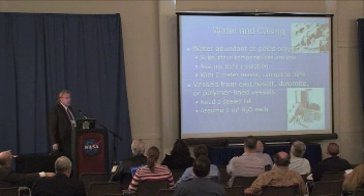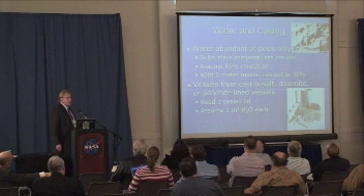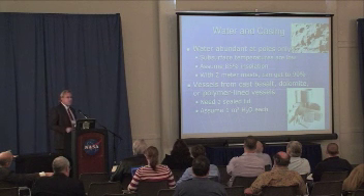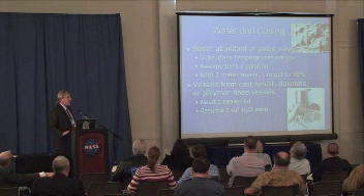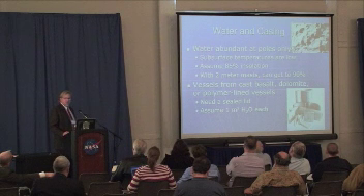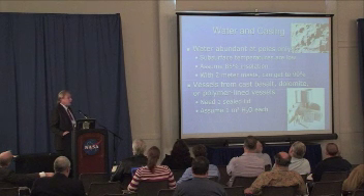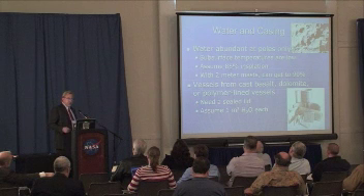The vessels can be made from cast basalt. Cast basalt is used traditionally on the Earth. What we're showing here are some cast basalt crucibles and other different kinds of structures that have been made from melting this material and squishing it into a form. You can make this into a vessel. The neat thing about this is that cast basalt can withstand up to 50% caustic solutions. We only need a 30% caustic solution for the Edison cell. So this stuff should be able to be used directly as is, without a liner.